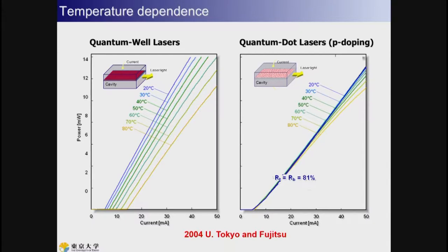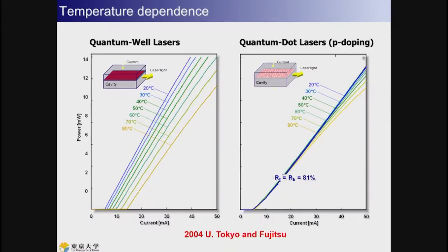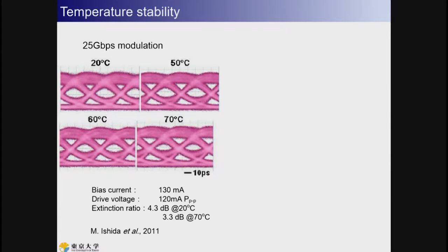This is the threshold current for the quantum well lasers and that of the quantum dot lasers. You can see the change of the threshold current with temperature for the quantum well lasers. However, for the quantum dot lasers, there's no change in the threshold current. This will be very useful for practical applications because we don't need any current or temperature adjustment. So this is the 25 gigabit per second modulation result in the temperature range between 20 degrees Celsius and 70 degrees Celsius without any adjustment.